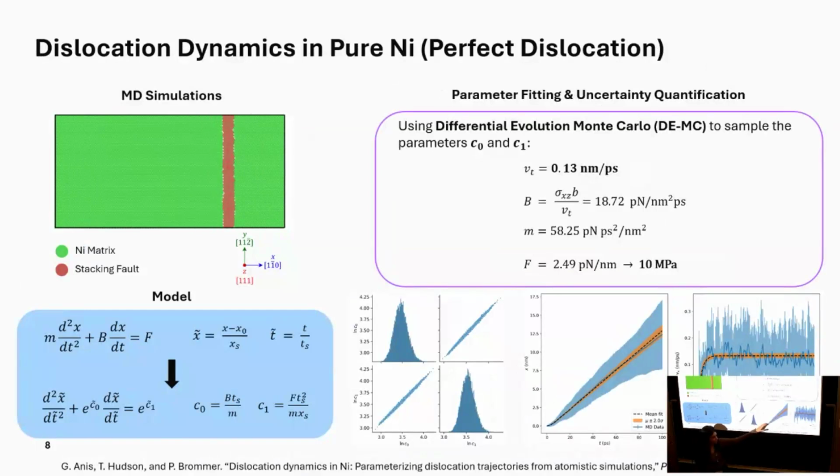In this low stress regime in the pure nickel, we get a lot of thermal noise that we are not capturing, so this uncertainty is also underestimated because we don't have anything in our model to capture those thermal fluctuations. So it is an issue here. As we go to the higher shear stresses in the data I showed later, the noise was less pronounced than this.